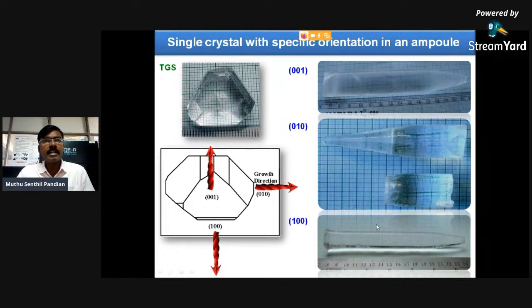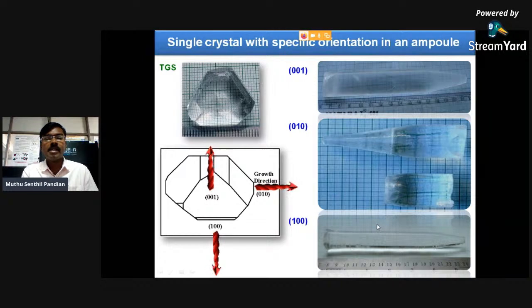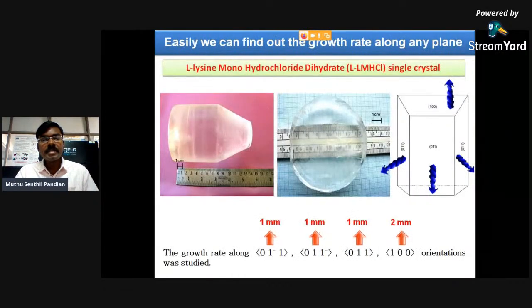The only thing is we have to identify which plane or which direction is useful. If it is an NLO material, it can be useful for SHG application. If it is a ferroelectric material, that polar B axis will be useful for ferroelectric application. So we have to identify that and mount it at the bottom of the glass ampoule. Then it is very easy to identify the phase matching direction, and we can easily find out the growth rate along any plane.